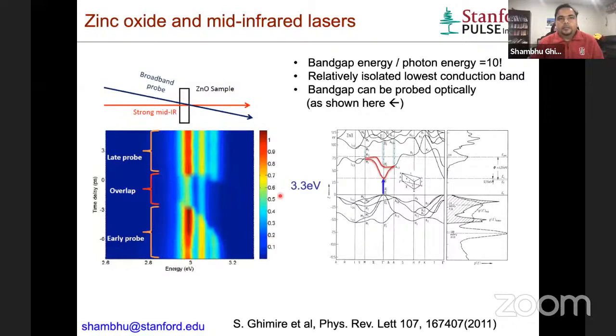So this was a good combination to achieve that: the sample zinc oxide and mid-infrared laser fields. You can see the band structure of zinc oxide. The main idea was that the photon energy is much lower than the band gap. In this case, the ratio of the band gap to photon energy is about 10. So this was a good choice. As you might recall, because many of us have been working on gas phase high harmonics, argon atom has an ionization potential of around 15 eV, and we typically use the 1.5 eV laser to excite. So that's a ratio of 10.